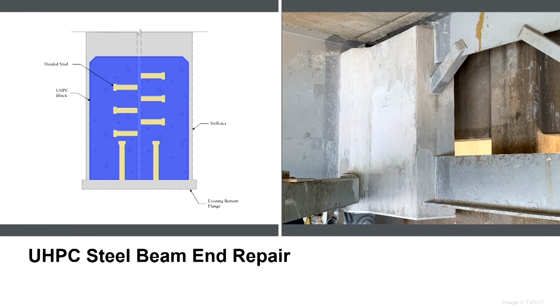For the steel beams, since we'll have UHPC contractors on site, we're going to use UHPC to repair some of the deteriorated steel beam ends. The way this works is that you weld shear studs in an array around the deteriorated steel and then cast a block of the UHPC around those shear studs to get composite action between the concrete and the steel and transfer the loads that would have been in the steel to the concrete. And the concrete has that compressive and slight tensile strength because it's UHPC. The added benefit of this is that when you're encasing the steel in the concrete with this low porosity, you get a protective coating around the steel to hopefully reduce any further deterioration of that steel.